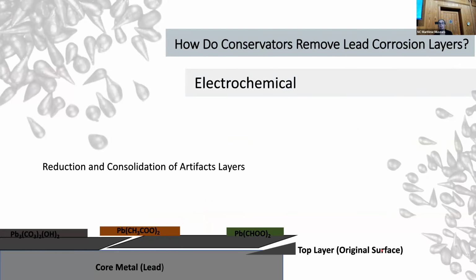Another technique we can use is electrochemical cleaning. So electrochemical cleaning basically uses electrical energy to essentially transform our corrosion products either back into metallic lead or into more stable corrosion products. It'll take that lead acetate, which is a reservoir of acetic acid, and transform it into something more like a lead oxide, which is a lot more stable.